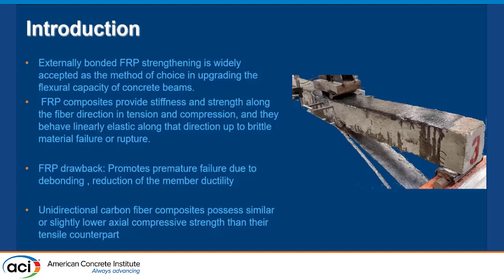However, there are some drawbacks in the FRP strengthening systems that sometimes limit the strengthening benefit. One of them is that it promotes premature failure due to debonding and a reduction of the member ductility. If we can mitigate all these, then we will get the maximum benefit of the strengthening system. The unidirectional carbon fiber composite possesses similar or slightly lower axial compressive strength compared to tension. If we can use this fact in our strengthening techniques, then we can utilize the material more efficiently.